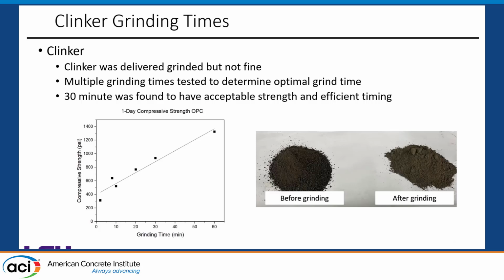For the clinker that we used in this project, we wanted to get raw clinker that wasn't already intermixed with gypsum so we could control the mix design better. Our clinker was delivered ground, but it wasn't truly fine. You can see that in the picture to the right, where there's still a good bit of pebbles and larger particle sizes in it. So we had to grind the clinker ourselves within our lab.